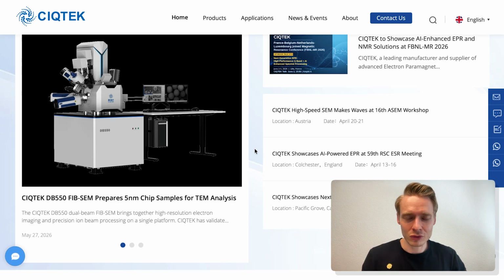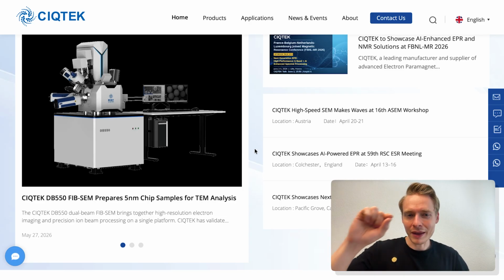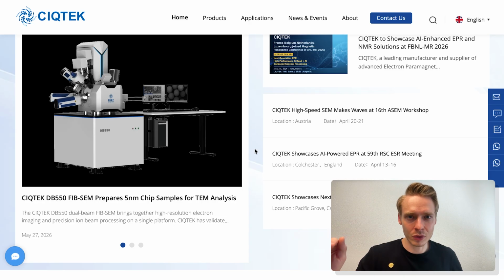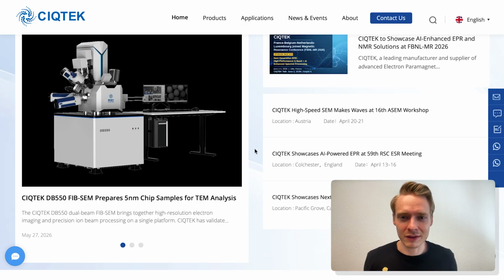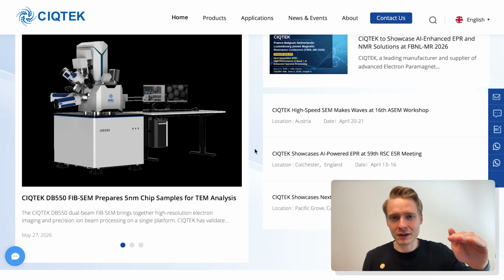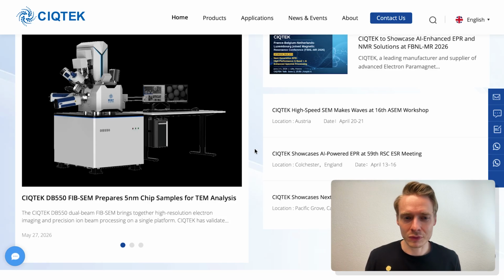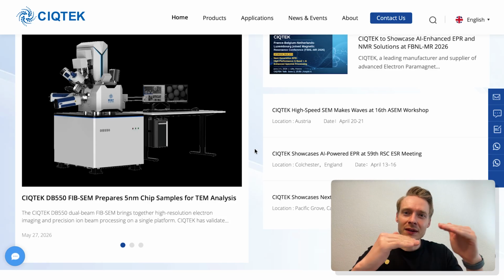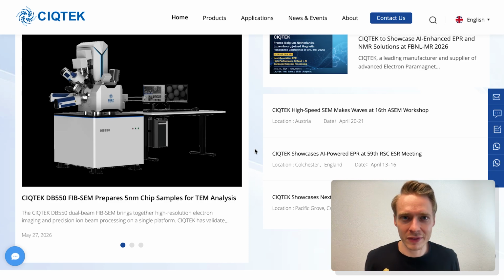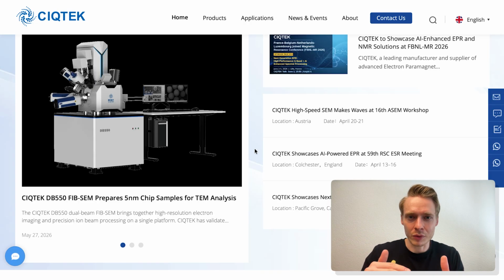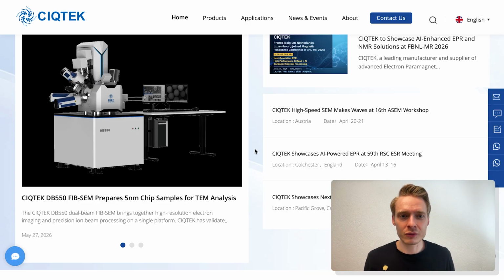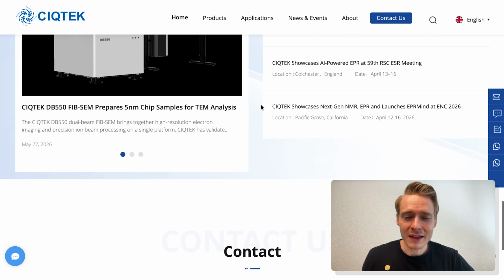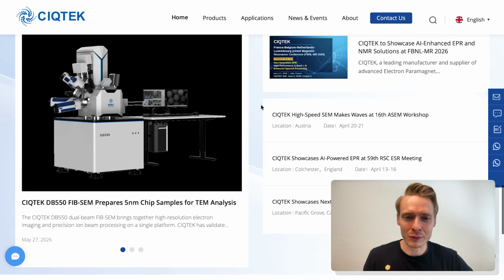And in a transmission electron micrograph, you can really see, let's say, the atom by atom setup. You can see how clean your transitions and heterostructures, for example, are. So heterostructures are, let's say, stacks of different materials on a wafer. Let's say you have a silicon wafer, you want to put silicon oxide and then silicon germanium on top, just as an example. You could look at this heterostructure in this transmission electron microscope, and you could see how clean those transitions are, if it's really stacking well on top of each other, and also how the crystal lattice looks like, if there's tension in the crystal, or if it's growing cleanly on top of each other. So you can do a lot of material research, which is very important for all of the quantum technology. That's, let's say, the zoom out on these microscope technologies.